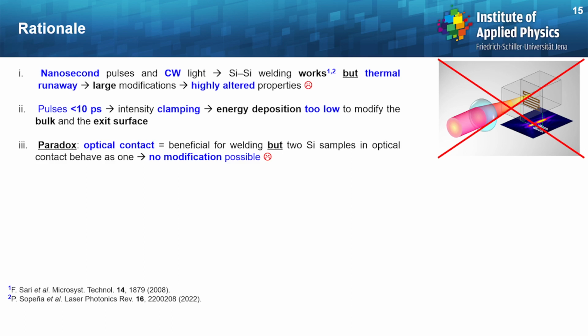But if two silicon samples are placed in optical contact, then by definition, they will optically behave as if they were one, right? And then because of point 2 here, one can conclude that no modification would be possible. As a nice way to sidestep this paradox, one may enhance the absorption at the interface.